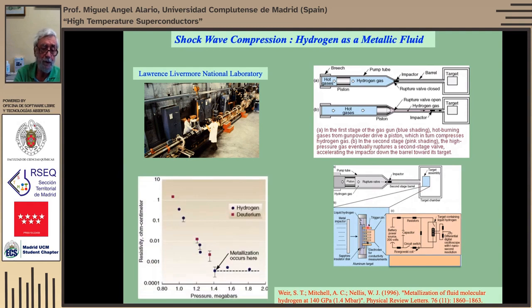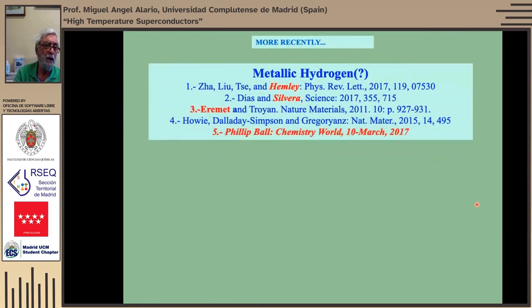If you measure the resistivity of the target as a function of the pressure, and the pressure depends on the amount of powder that you put here, you see that the resistivity diminishes, and then finally is very low and constant. So you get a process of metallization. That's the first experiment, back in 1996. I also know Nellis, and he was very proud, but not everybody believed this experiment. Anyway, this is metallization. Now, more recently, there is a lot of work on this.